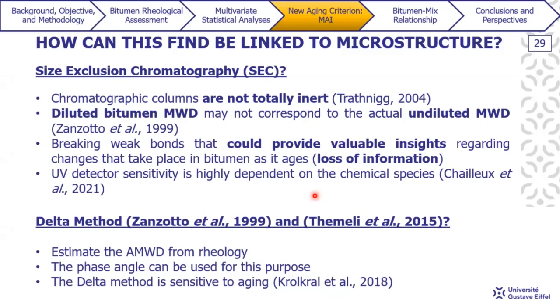For example, chromatographic columns are not totally inert. The molecular weight distribution of diluted bitumen, in this case, may not correspond to the actual molecular weight distribution of undiluted bitumen. And also breaking weak bonds that could provide valuable insights regarding changes that take place in bitumen as it ages could make us lose important insights on the aging phenomenon. And also UV detector sensitivity seems to be highly dependent on the chemical species. In this case, there's the delta method, which is an alternative to overcome these limitations, because the delta method proposes to estimate an apparent molecular weight distribution based on bitumen's rheology.